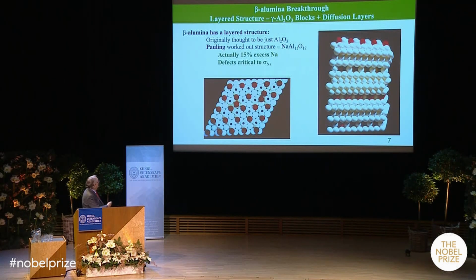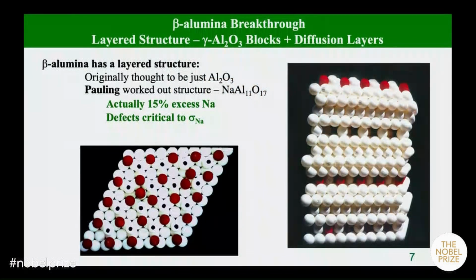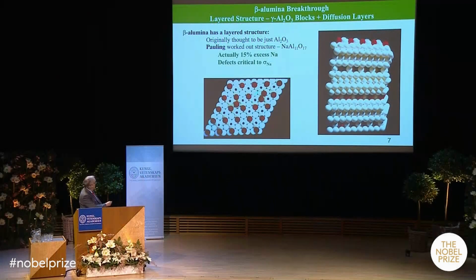Let's look at what is special about beta alumina. And there's some big names here. This is a layered structure. So 4 layers of oxygen in this very open structure, another 4 layers, very open structure. For many decades, this was considered to be just aluminum oxide. But it was Linus Pauling who worked out that this material's got sodium in it, and it's the sodium ions that sit in these layers, and I've shown them here in red. And what we found out later, this material has about 15% excess of these ions, and that's what lets the ions move very, very fast.